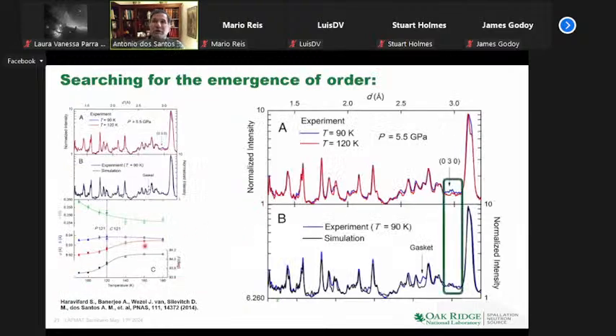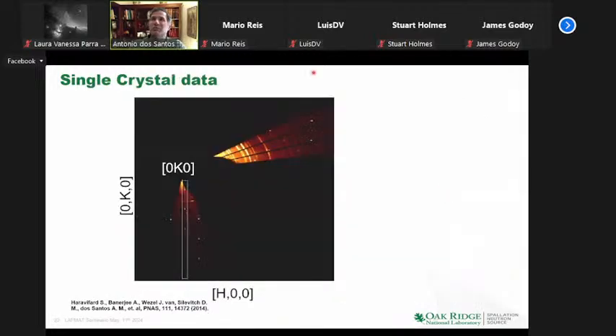Earlier work with X-rays knew there was a phase transition, and we came and did some neutron work on powder. But the question is, if you're breaking this frustration, does anybody really believe that this is a magnetic peak? It will be a very hard sell. So what we did is that we measured a single crystal, the same crystal as that.